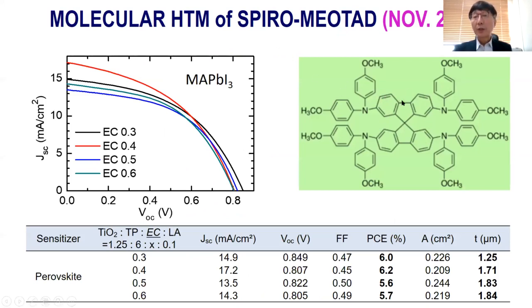So I wanted to switch the polymer material to a molecular hole transporting material such as the spiro compound. Shown here is the spiro backbone. We tried the spiro compound and saw a small increase in the power conversion efficiency. However, when we changed the film thickness from 1.2 micrometer to 1.8 micrometer, the efficiency would not go up. Therefore, we would like to find some useful method to improve the efficiency.